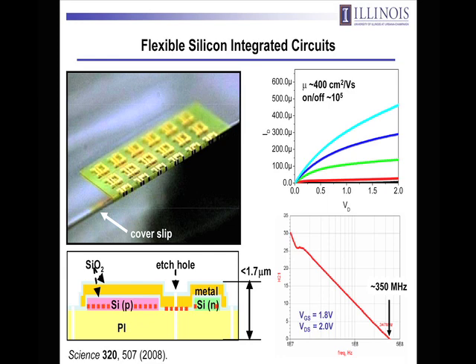You can be a little bit smarter than that, though. You can actually choose the thickness of the polyimide substrate such that the neutral mechanical plane is coincident with the silicon, which happens to be the most brittle material in this simple integrated circuit. And you can think of the neutral mechanical plane as a very simple thing. If you have a sheet of plastic, if you bend it like this, then the top surface is in tension, the bottom surface is in compression. The geometrical midpoint corresponds to the point through that cross-section where there's zero bending-induced strain. That's the neutral mechanical plane. It's the geometric midpoint in a uniform sheet of material.